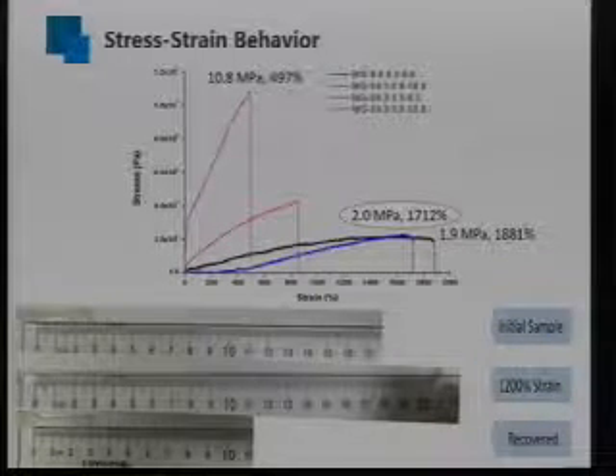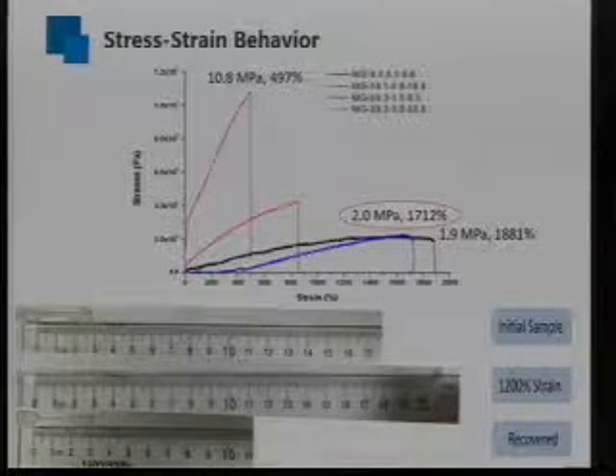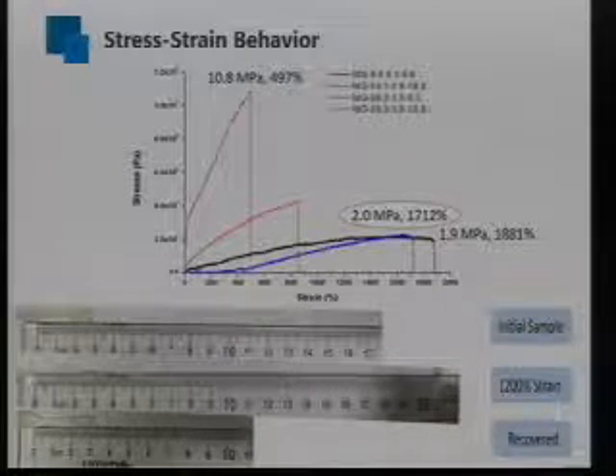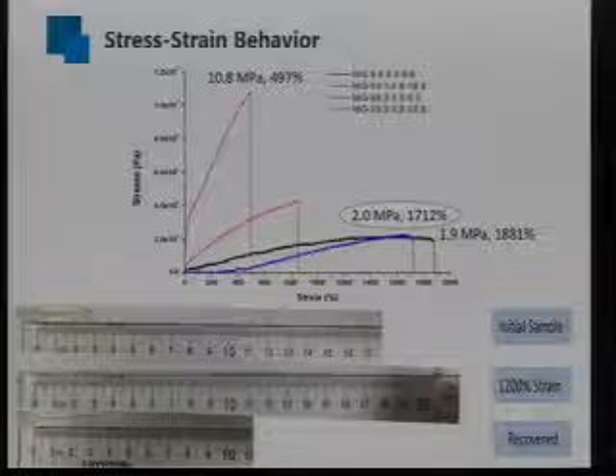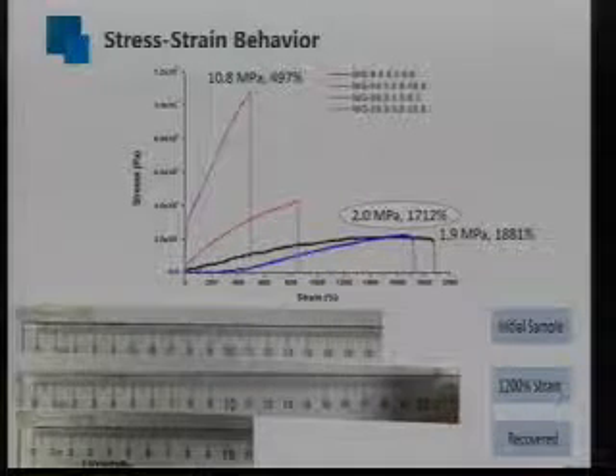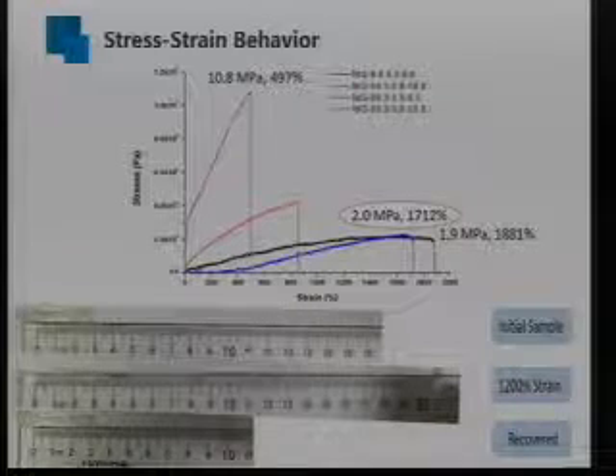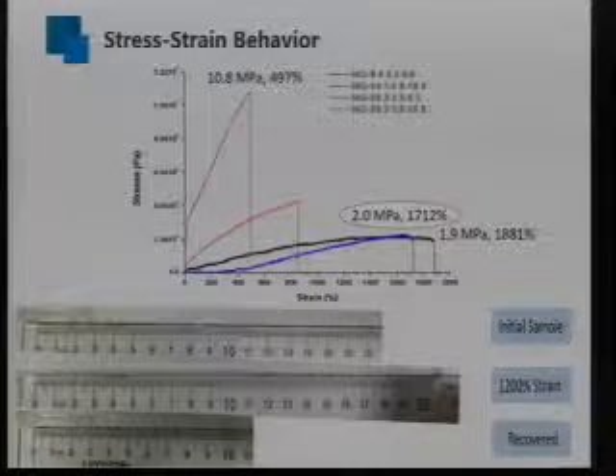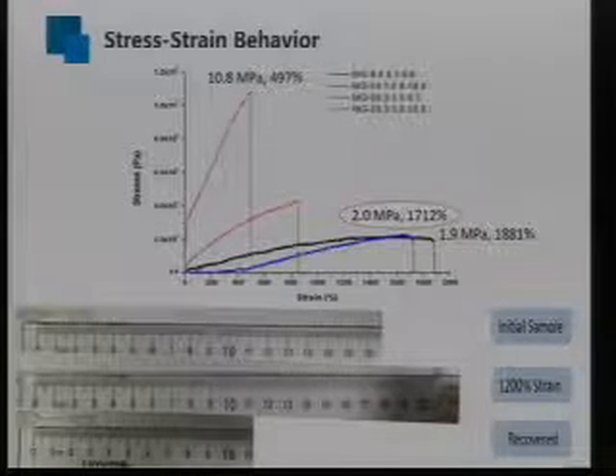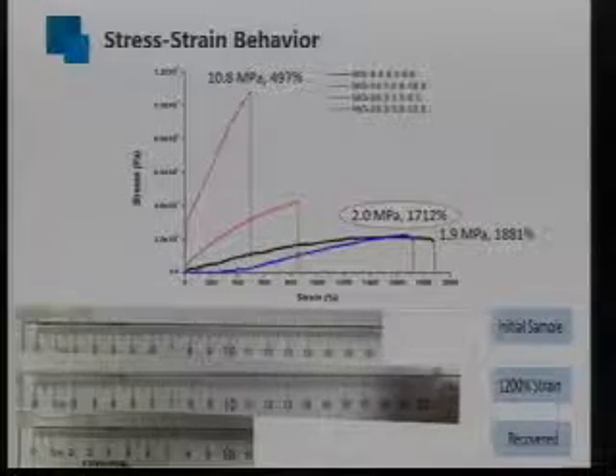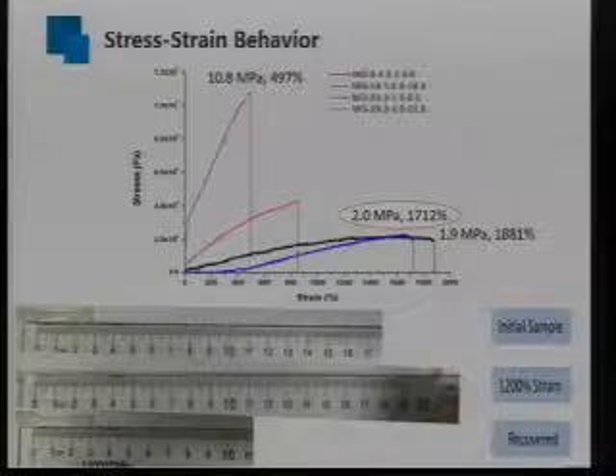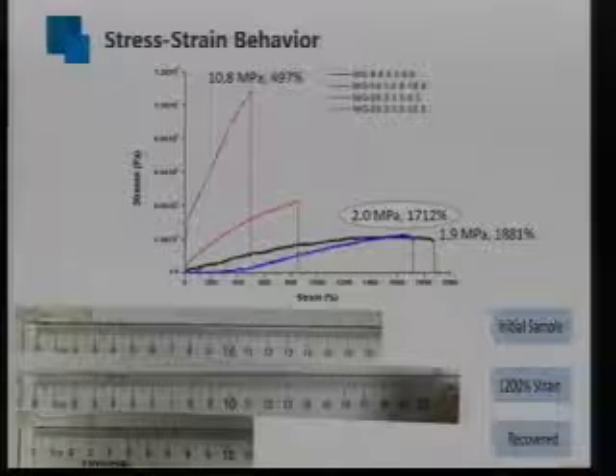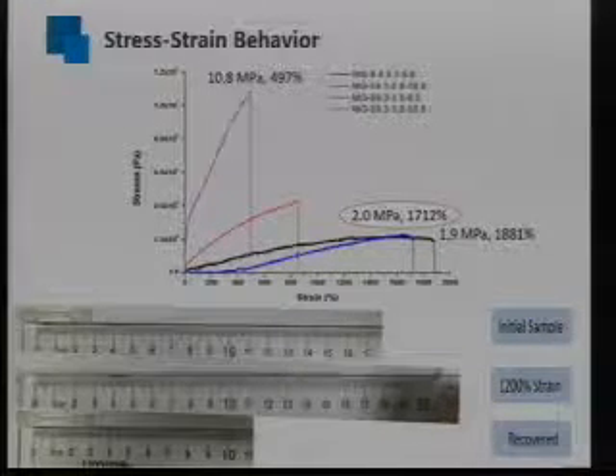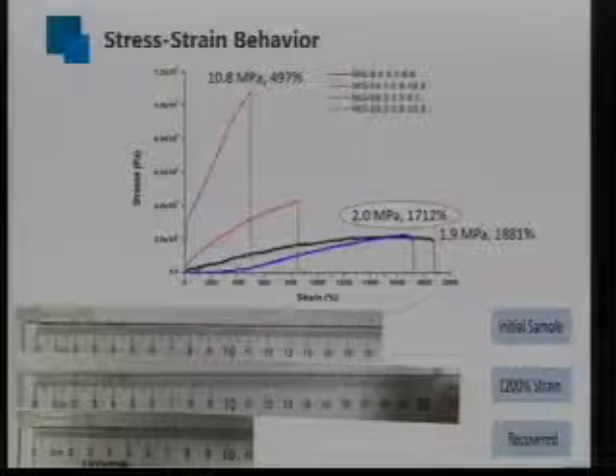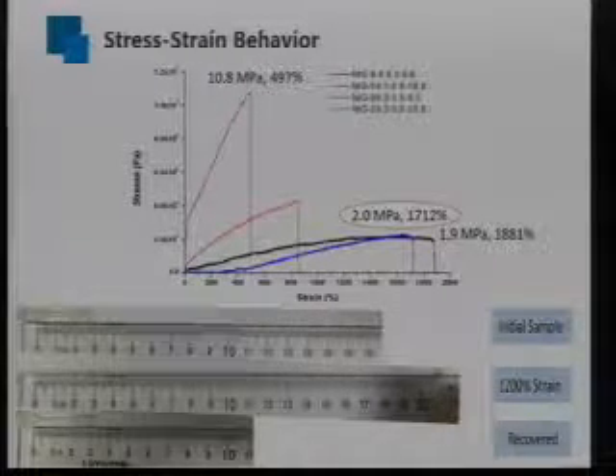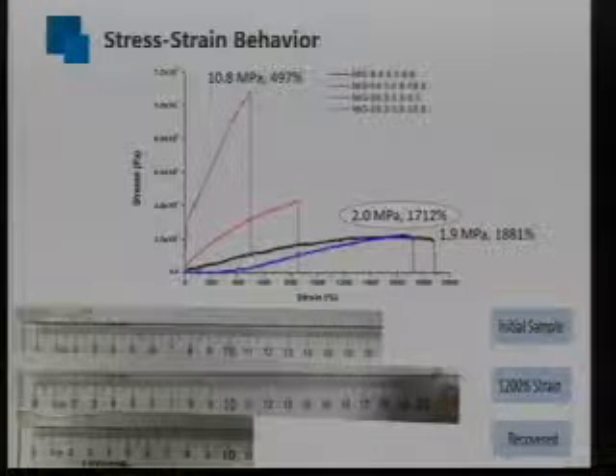The stress-strain behavior of these materials was characterized by uniaxial tensile testing. With the volume ratio of the PMMA as high as 33.8%, the material reached a mechanical strength as high as 10.8 megapascal, but with the elongation still around 500%. Then, with the PMMA molecular weight of 29.3 kilograms per mole and a volume ratio of 9.3%, it gave a stress as high as 2 megapascal and an elongation higher than 1700%.